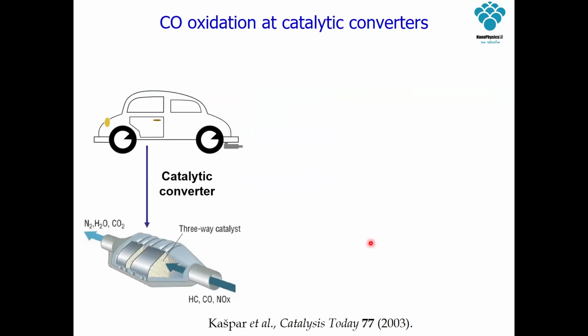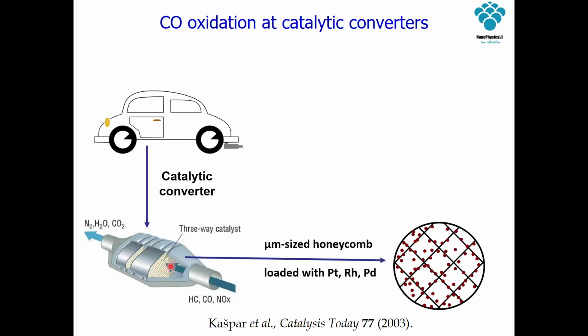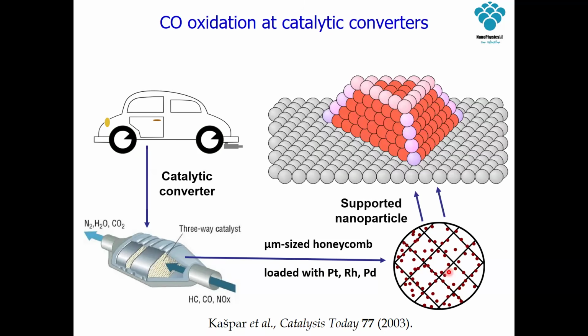So basically, again, on the bottom of the car, we have this catalyzer, the gases come in, and when we have a look at the inner part here, we have seen before this was this porous material, and on top of this porous material, we have these nano-sized particles of these catalysts, so platinum, rhodium, palladium, iridium, some of these materials. And when we have a closer look at them, they look like what you see here.